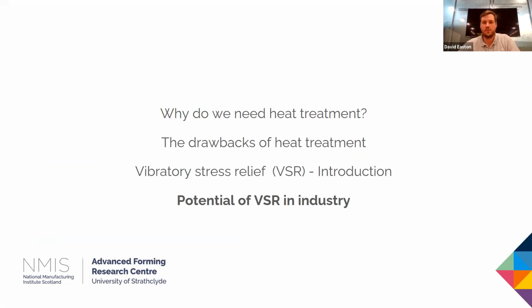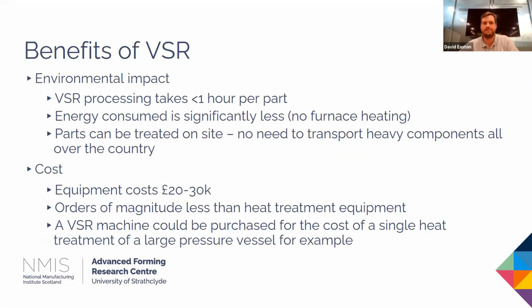and now looking at what the potentials of VSR in industry are. All of these points here are basically relating back to the issues that we can have with heat treatment. So environmentally, VSR processing takes less than an hour per part. The energy consumed is significantly less.